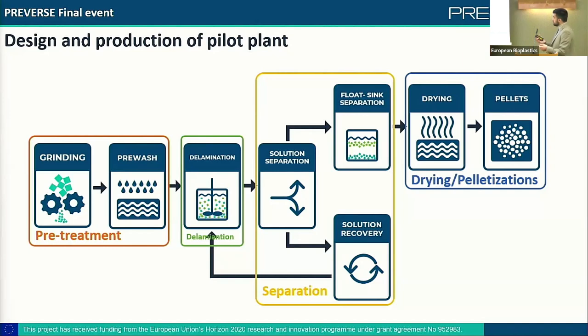And once ground, the material was washed to remove unwanted residues with which the material has previously been in contact. After this, the material goes to the delamination step, and in this block, the material is delaminated to separate the single layers of the material. After that, the material goes to the separation, which involves the separation of the material from the washing solution, and if the